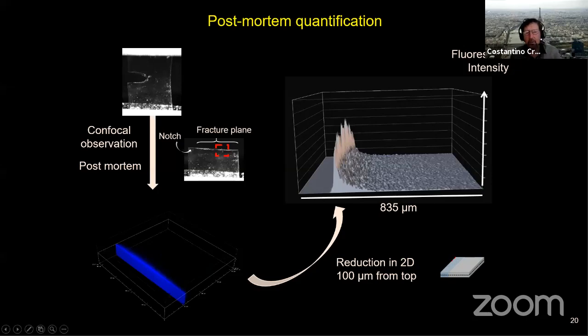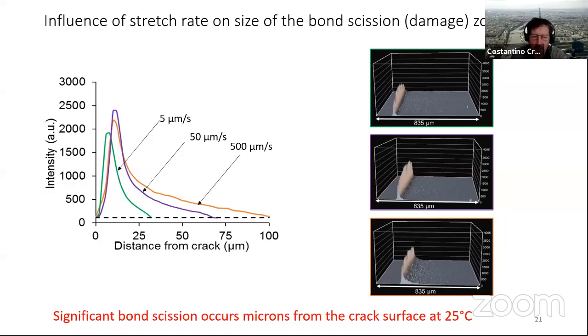So what we found, and this is just a first result I'm showing, is that if you actually do the experiment at different rates, so we break the sample at different rates, you don't see the same bond scission profile. You can see that at very low rates, it's more localized than if you actually break it faster, where you can see here much more bond breakage at a certain distance from the crack tip. And we certainly see bond scission microns from the crack surface, tens of microns from the crack surface. So this is not obvious, I think, from the point of view of mechanics.